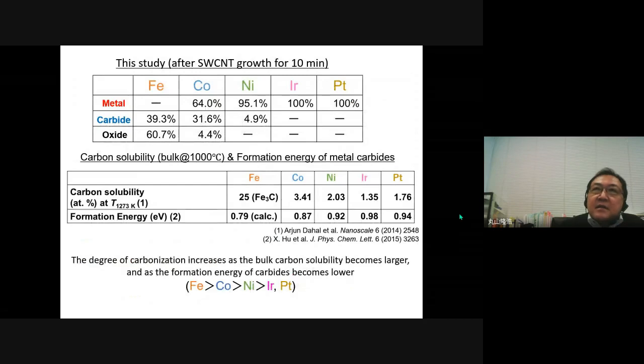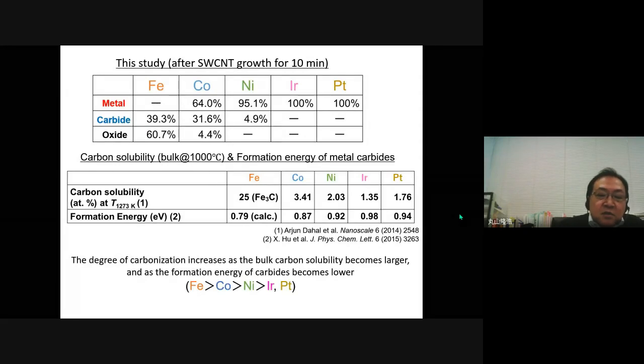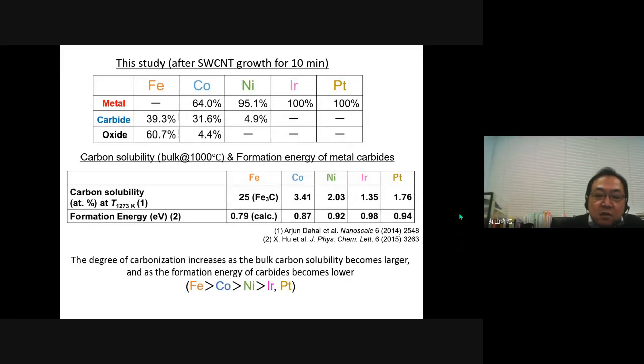This summarizes the ratio of metal and carbide for each catalyst metal during nanotube growth. The lower table shows carbon solubility and formation energy of interstitial carbon for each metal. As you can see, as the bulk carbon solubility becomes larger and the formation energy of carbides becomes lower, the degree of carbonization increases. Next, please.